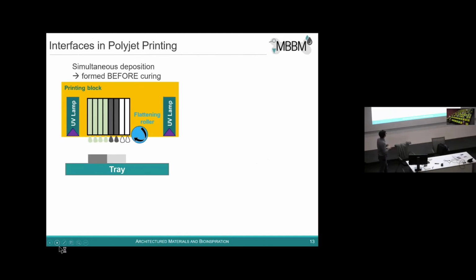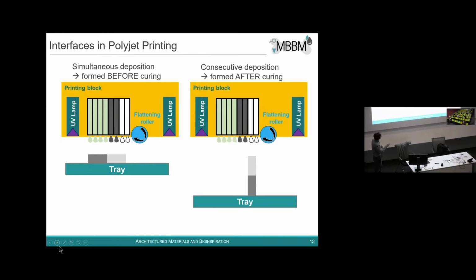If you go into the details of the printing process, there are 2 different ways that 2 polymers can get in contact. You can have a simultaneous deposition of the two polymers, which are represented here with the 2 colors. So they are deposited simultaneously, and they get in contact on the build tray before being cured by UV light. Or they can be deposited consecutively. You first deposit one polymer and then cure. And then on top of an almost fully cured polymer, you deposit the second droplet here, and then you cure this. So here the interface is formed after curing, and here the interface is formed before curing of the 2 polymers. And we are asking what the properties of the interfaces are in these 2 different scenarios.